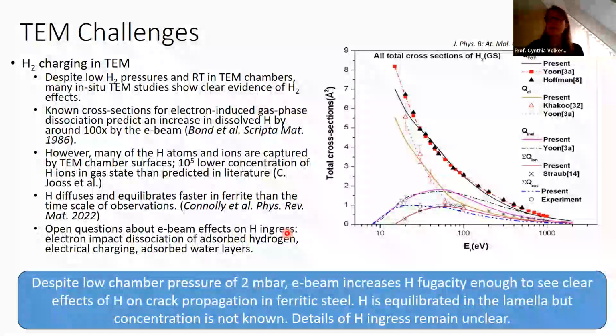Despite that, in a number of different materials, various studies across the world for groups that have these environmental TEMs have found that despite these low pressures and despite room temperature, one sees hydrogen effects on the material. So the conclusion is that in some way or another, the electron beam inside the microscope is significantly increasing the fugacity of the hydrogen, so that we're producing enough hydrogen in a state that it can get introduced into the ferrite in this case, or into the other materials and other studies, that in fact we do have significant hydrogen in the material.